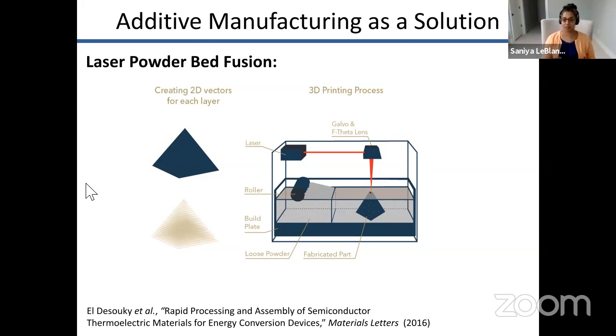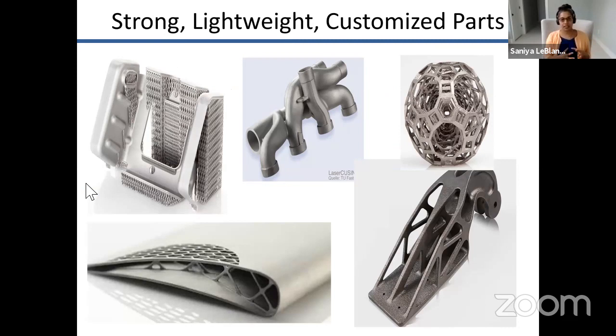And we looked at different additive manufacturing techniques and settled on a technique called laser powder bed fusion, where parts are made layer by layer by laying down a layer of powder and melting it in a certain pattern. It solidifies, and then you build up a part layer by layer. So this is a 3D printing technique, if you will, in layman's terms, that is used primarily on materials like metals and ceramics. And this technique can give strong, lightweight, customized parts with small, complex features.